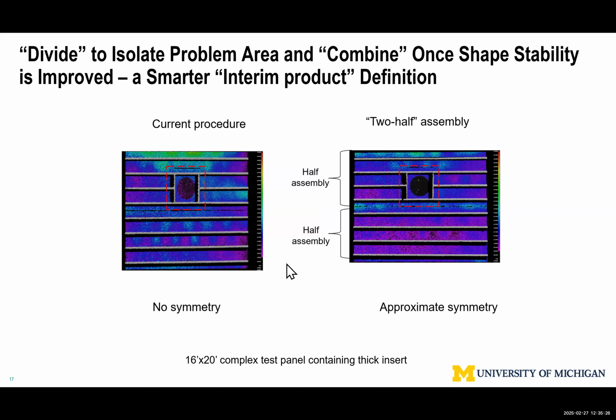This one we call complex panel. We tested in one major shipyard. This part has a 10 mm insert, rest of them is 5 mm with T stiffener. Obviously, by definition, no symmetry. They put the bottom wall together, put two plates, and then assemble stiffener. Actually, when we run into this situation, we talk about divide, combine, and conquer. That means if you don't have an opportunity to change the design, when somebody gave you this design, what we can do is let's isolate the part that doesn't offer symmetry, add a lot of complication.